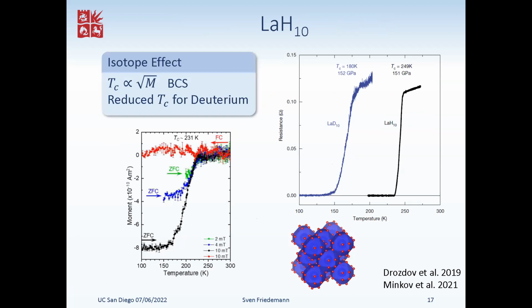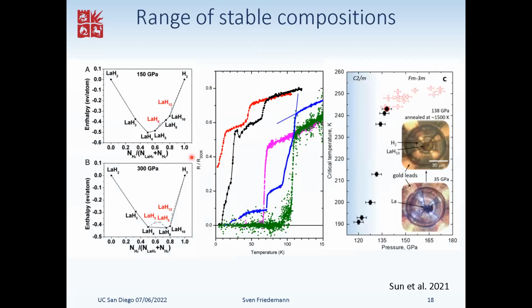So for lanthanum H10, these are data reported by Eremets' group with a resistive transition at about 250 Kelvin and a diamagnetic signal at a similar, in this case a bit lower, temperature. The challenge with these materials is that you can form multiple phases. What is typically looked at from an ab initio point of view is the convex hull, which calculates the enthalpy of different stoichiometries, and anything that's on a convex hull formed between the end members, which could be lanthanum and hydrogen, or here they've chosen LaH2 as the lowest binary, is stable as a ground state.